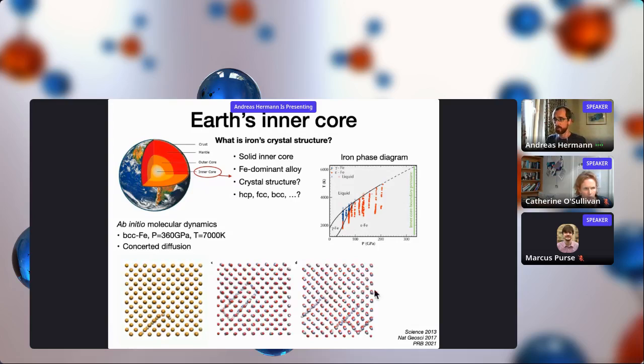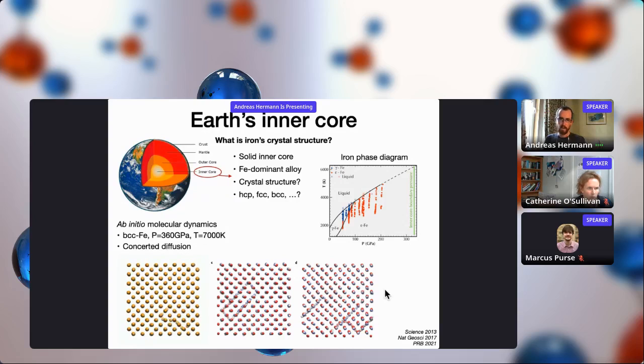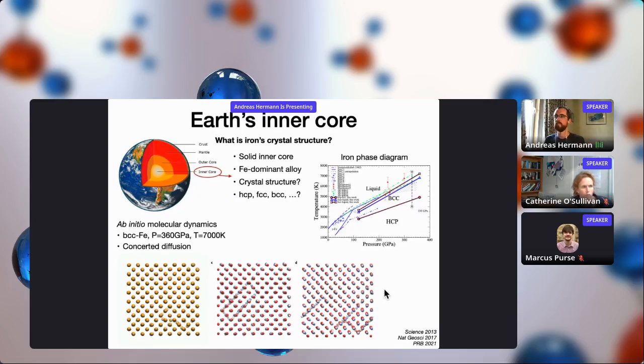If you plot the time average of this trajectory, then you can see these atoms move around in rings or maybe along lines, and maybe they intersect or go around a corner or not. It seems to be quite a curious little effect, but it does lower the free energy of BCC iron to the extent that in the latest calculated phase diagram of iron, there's a big sliver of this BCC phase present in PT space above the HCP phase as a high temperature phase.